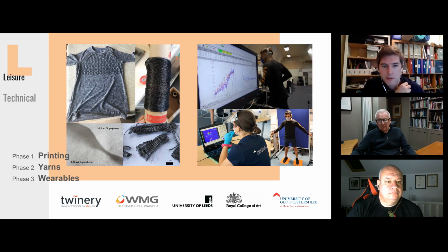So again, one of the key issues with the textile sector is kind of degradation of clothing and shedding of microfibers, which again can cause some environmental issues. So we're really looking here at, can we improve, and we have demonstrated quite significant improvements of mechanical performance of yarns. And we're now going towards really kind of, as I say, moving out of the lab into pilot scale production and demonstrating. A year ago, we were making fibers which were sort of 100 microns in diameter. Now we're down to sort of 3 or 4 microns. And also we're making non-woven fabrics from those non-woven mats, as well as the traditional woven textiles.